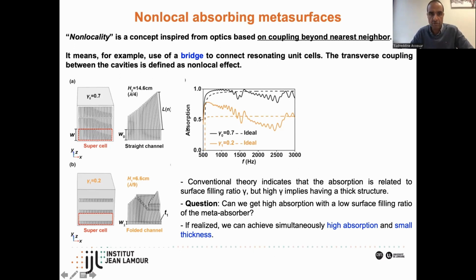We can see that, of course, we have a large band gap, but we are not in the extremely challenging low frequency. We are above 500 hertz, which is still challenging, but not as challenging as the other ones. So we can get broadband, no problem, that works fine. But the problem is that the thickness is a little bit higher. Why? Because if you see the conventional theory, the quality of absorption is related to what we call the surface filling ratio.